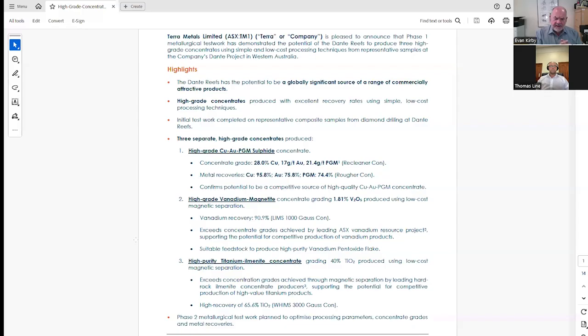If one looks at the Largo and Chinese experience, they are producing concentrates of sort of 10 to 20% TiO₂ by magnetic separation, and then using froth flotation to upgrade. Our mineralogy is better for titanium production, and this first test has produced 40% ilmenite concentrate. Just by magnetic fractionation, there's a very good chance we'll get to 46, which is a saleable grade. And if not magnetic fractionation, we can use the same flotation processes used in China and Brazil to take this to a super grade, a saleable grade ilmenite concentrate. That's an overview of the work, and I've tried to include an overview of the economic significance of the test work. Tom, back to you.